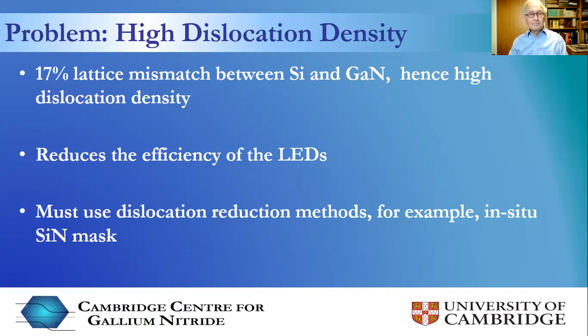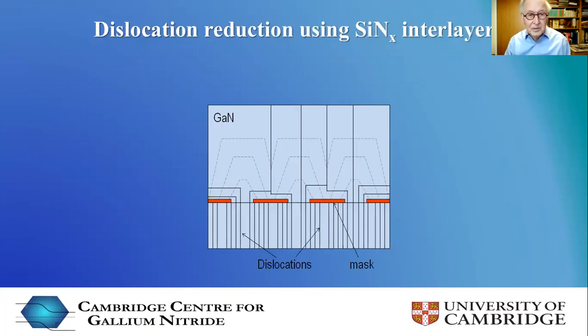Can we have the next slide please, which shows this. So this red color here is the mask, a silicon nitride mask. Underneath that we have gallium nitride with all these threading dislocations propagating upwards. And when the dislocations hit the mask, they stop - they won't propagate through. But when they hit the holes in the mask, they propagate through. So you immediately get quite a big reduction in dislocation density just by having the masks.